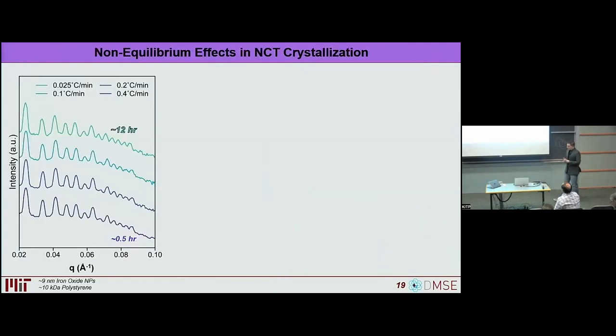So continuing on to another example of this idea of transformation and odd things that happen in the nanoparticle assembly case. Let me go back to that idea of being able to assemble these materials very rapidly. One of the things we were excited about was understanding how different crystals will nucleate and grow depending on different variables like the cooling rate or the concentration or particle size, etc. So I had one of my students, Matt Ye, go back and recreate some of the work that we had done previously. At this point, we've moved from gold particles to now iron oxide particles because they're a little bit more scalable and we can make larger quantities of them. But the assembly process is still the same. It's still the same DAP thymine guided formation of BCC lattices.